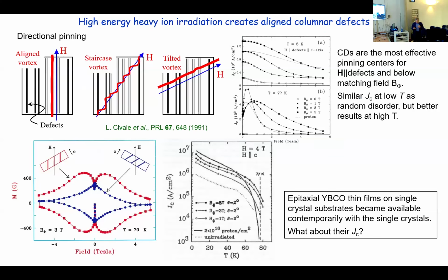Then I did the experiment that introduced directional pinning by very heavy ion irradiation, very high energy, and we produced columnar defects. And these columnar defects had the characteristic that the pinning is directional, so it's very strong when you apply the field parallel to the defects, less so when you apply the field tilted to the defects. And we showed that by measuring the hysteresis at 2 different crystallographically equivalent orientations, but one parallel and the other one not parallel to the columnar defects.